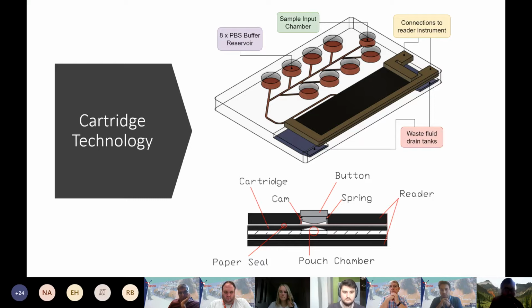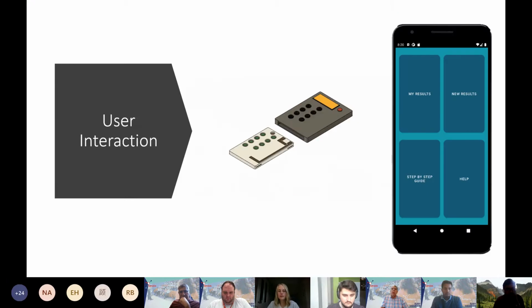So we are able to dip the entire cartridge in 95 degrees boiling water because all of the materials and the binding elements we've ensured are able to withstand 95 degrees temperature, and we're using a water bath, so there's no additional chemicals being added. The urea wash will be inserted into the sample chamber, so that will just run through the entire flow system and wash out unbound HA. Just to add to that, maybe you're a bit confused with the reader unit, which you can see here. That's the only thing that will not be dipped, will not be regenerated because it won't be needed.